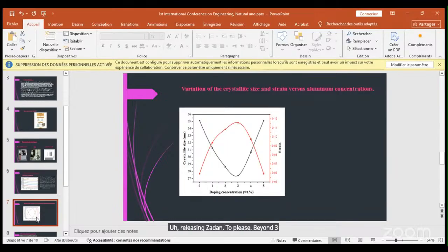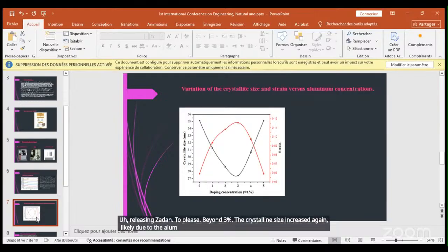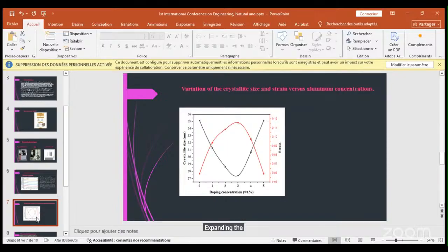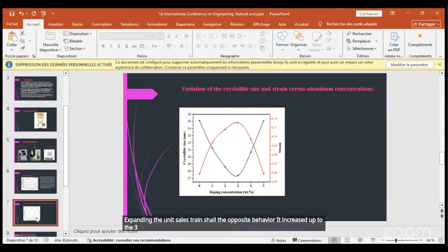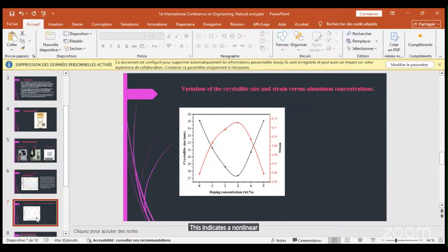the crystalline size increases again, likely due to the aluminum accumulating in interstitial sites, expanding the unit cell. Strain shows the opposite behavior. It increased up to 3% due to the lattice distortion, then decreases as the structure stabilizes. This indicates a non-linear, anisotropic structural response to aluminum doping.